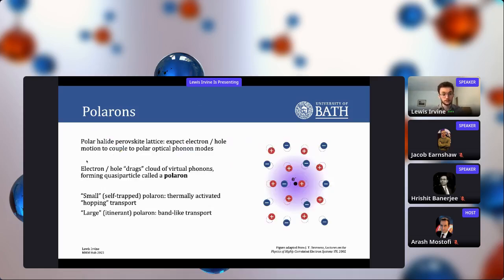So a polaron is formed from the interaction between a charge carrier and the sort of ionic lattice that surrounds it. So electron or hole motion can couple to particularly LO phonon modes in ionic lattices. And then if you try to move that electron or hole around, you can think of it forming a quasi-particle that's called a polaron, which consists of this electron plus the lattice distortion.